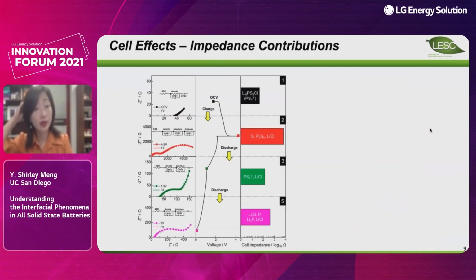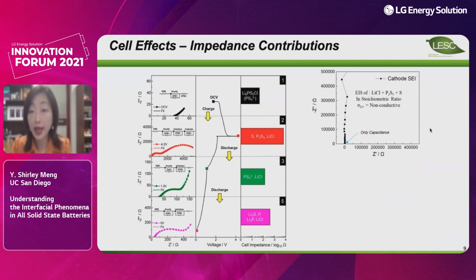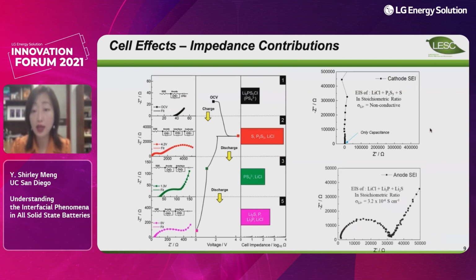One of the most critical experiments we've done is to look at the impedance change on the anode versus cathode. A 3-electrode experiment is also applicable in solid state batteries. When we look at the impedance spectroscopy, you can clearly see the difference between the anode SEI versus the cathode SEI. On the anode side, we are lucky because the product is a very good lithium ion conductor, so we can get a reasonable conductivity curve at room temperature. We're not as lucky when a large amount of sulfur is generated on the cathode side.